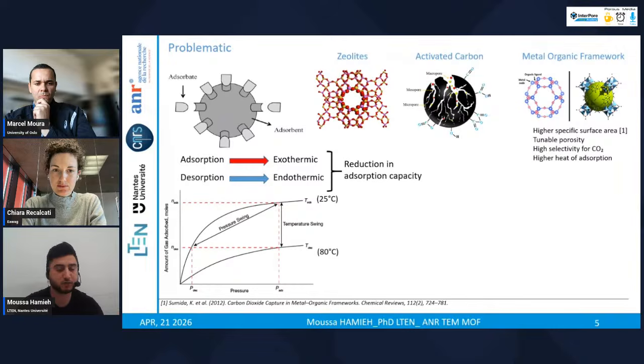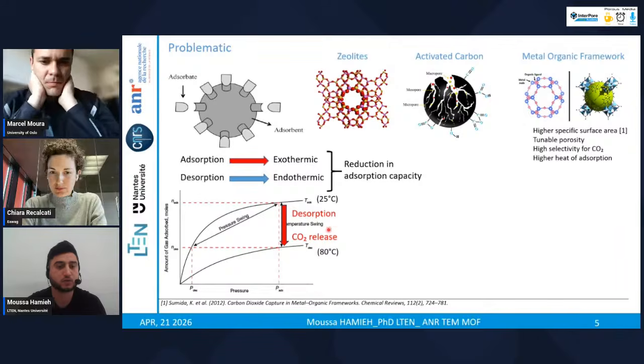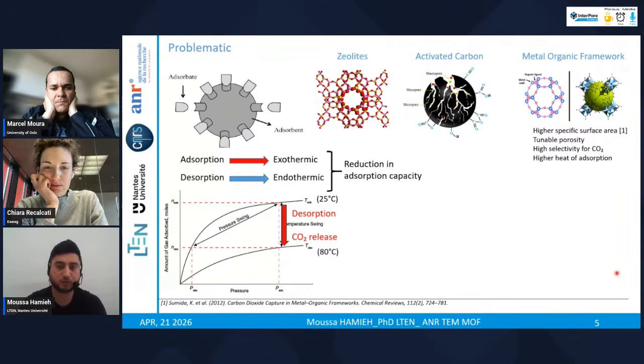Here we should note that the TSA, temperature swing adsorption, is known as a process that is more effective than the pressure swing and the vacuum swing adsorption, but it also requires too much energy, and this is a limitation in this process. So let's go back to our isotherm. At low temperature we have a higher amount of gas adsorbed compared to the isotherm with higher temperature. What's happening during adsorption is that heat is released because it's exothermic, and since MOF is not a thermally conductive material, the temperature of the MOF increases and we risk having hot spots. Since the temperature is increasing, it passes from one isotherm to another with higher temperature, and this isotherm has a lower adsorption capacity for the gas, so the MOF is more likely to desorb instead of adsorbing.